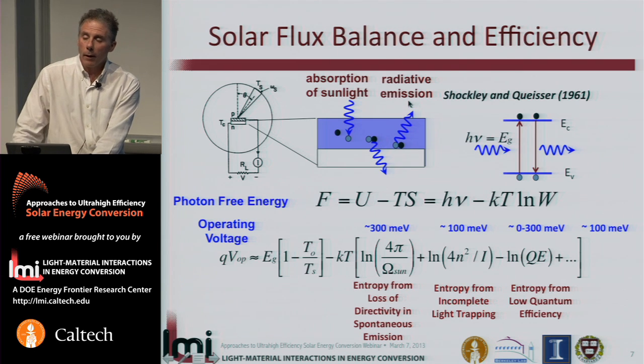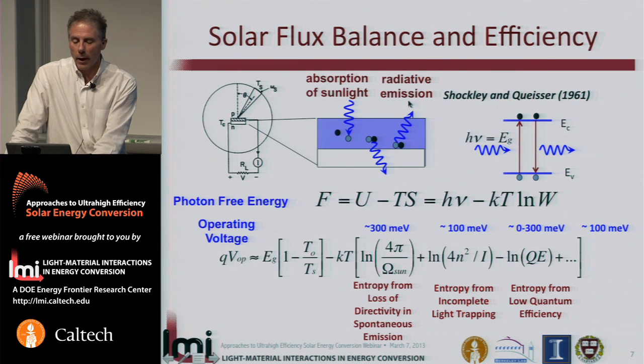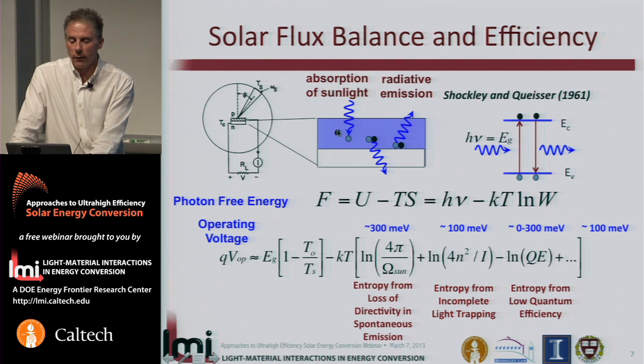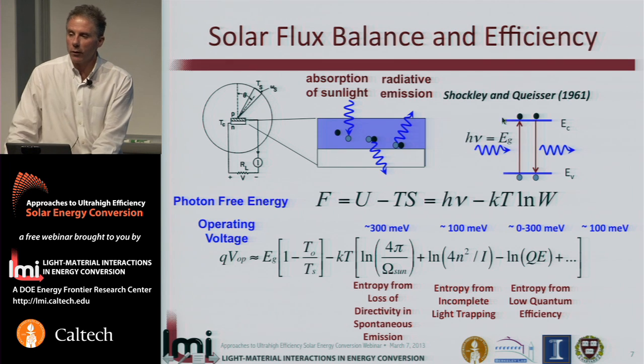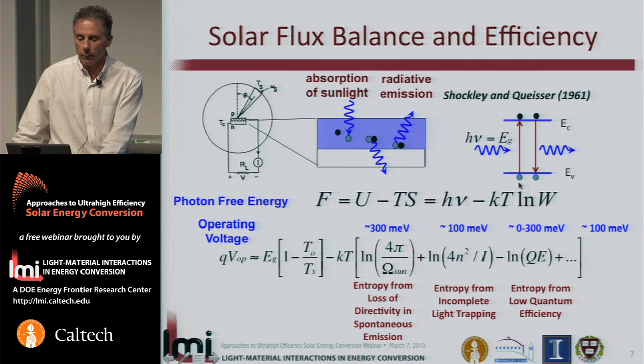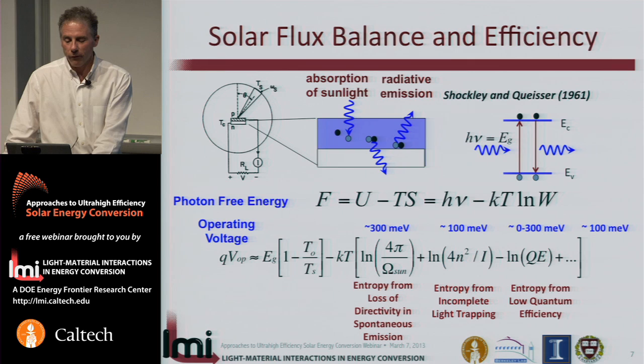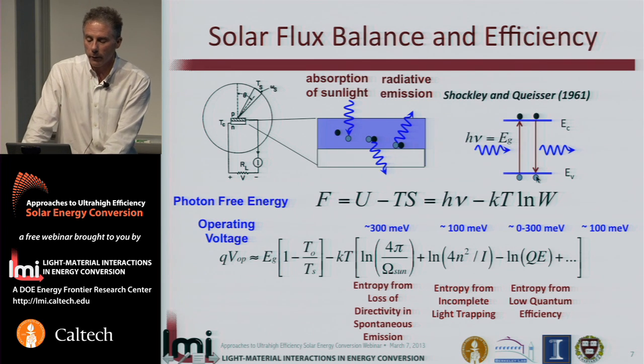Now, if we add to this detailed balance flux picture, and in fact the Shockley-Queisser model really is just a flux balance picture, if we add to this picture now an energy diagram depicting simply in schematic terms a valence and a conduction band for a semiconductor, we can see we're photoexciting carriers from the valence band to the conduction band by photoabsorption and balancing that by radiative emission, by radiative recombination from band to band.